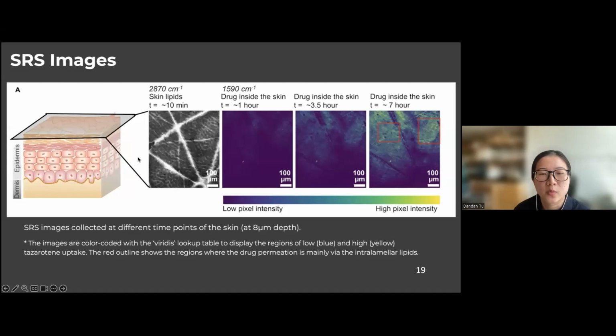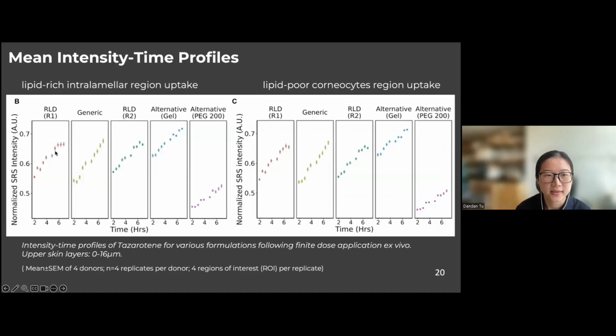And here are the SRS images we collected in this study. Those blue images are from the drug wavenumber, and we see the drug distribution change after we apply the drug on the skin as time goes by. At the same time, we collect the image from the lipid channel, which helps to show the microstructure of the skin. We will use this microstructure to extract the drug signal in the lipid-rich intercellular region and the lipid-poor corneocyte region, and then we can obtain the intensity time profile in those two different regions. The left-hand side is the lipid-rich region and the right-hand side is the lipid-poor region.